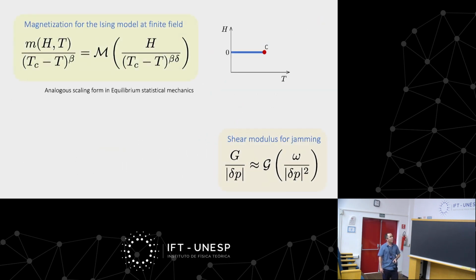So you might be familiar, for instance, with an example for magnetic systems, the Ising model. You have a phase diagram in terms of magnetic field and temperature, and the first order transition line that ends at a critical point there. And you can find something that is very similar here for the magnetization as a function of field and temperature. There is an overall power law here, times some universal scaling function of this invariant scaling combination.